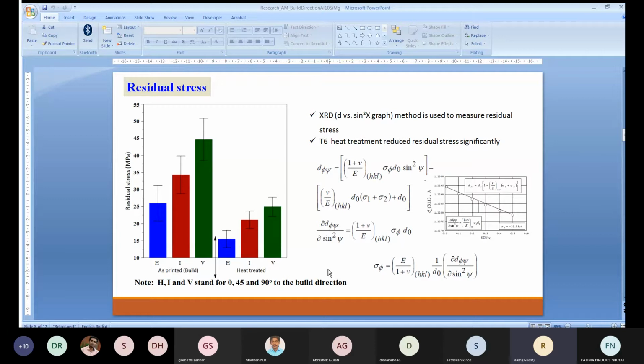So you can see at the bottom the equation, that is Young's modulus by 1 plus Poisson ratio, and the diffraction peak which you have used, that is HKL, and 1 by d naught. d naught is nothing but your interplanar spacing in the stress-free state, and dou d by dou sine square psi is nothing but the slope of the curve. So if you plug in all the parameters, you will get the residual stresses.